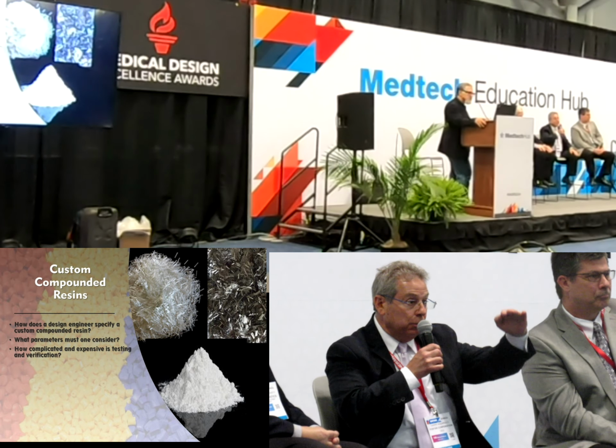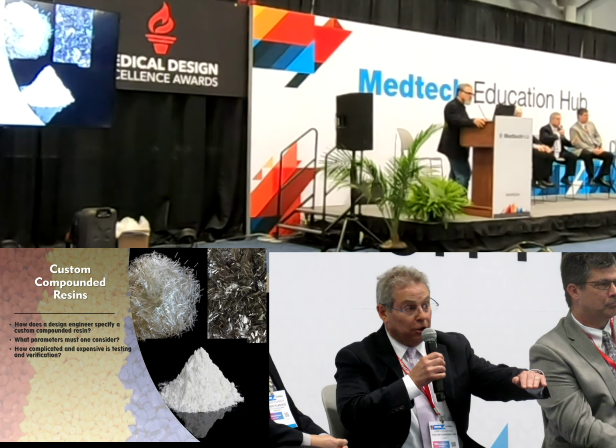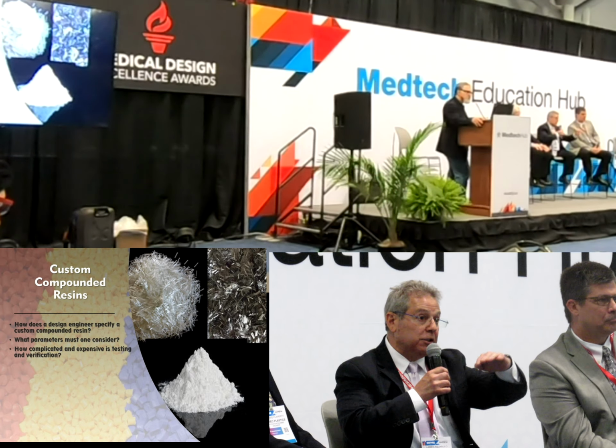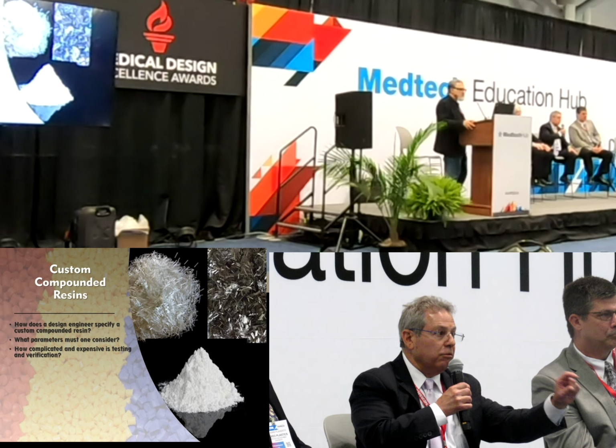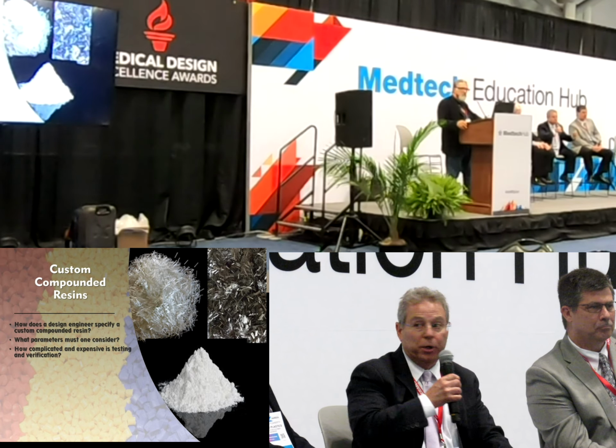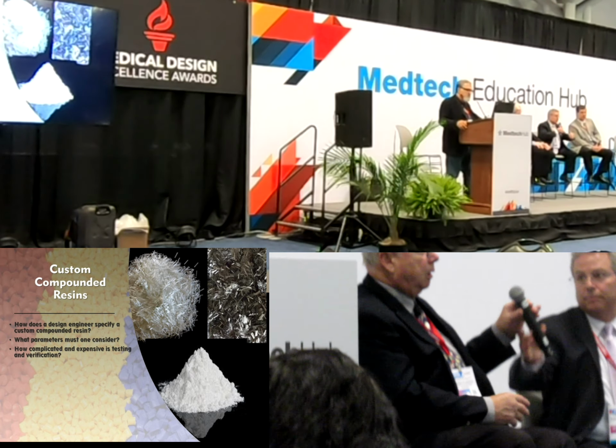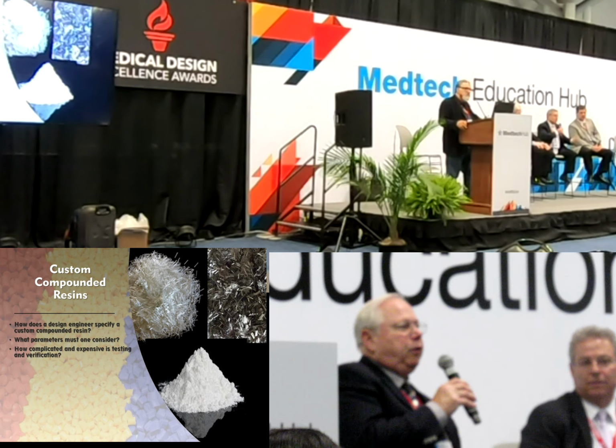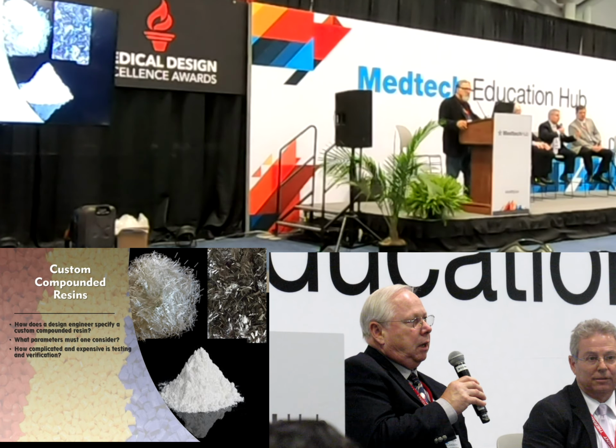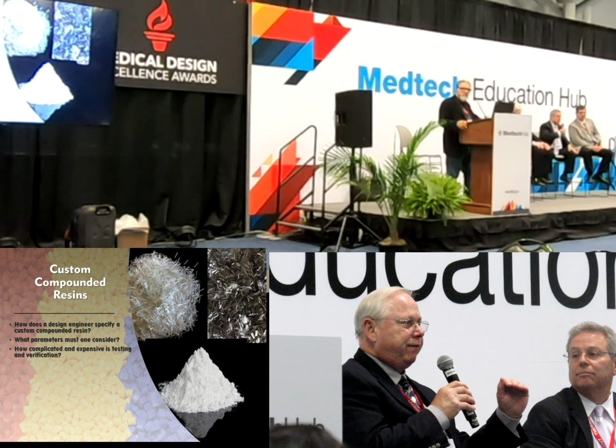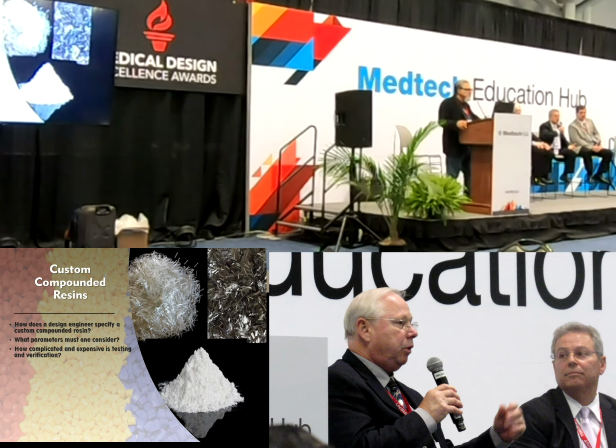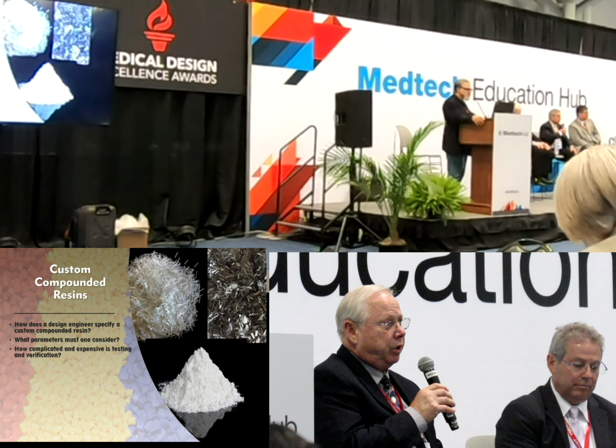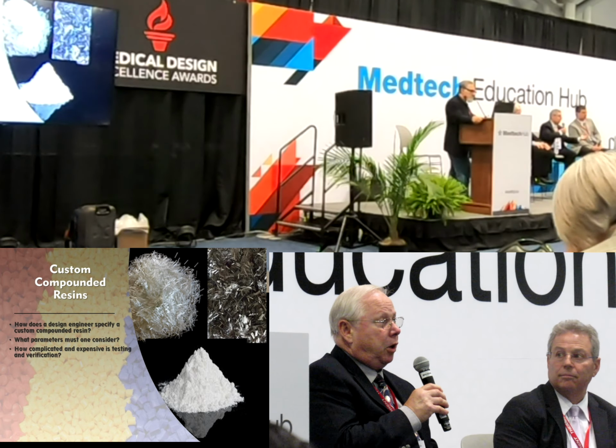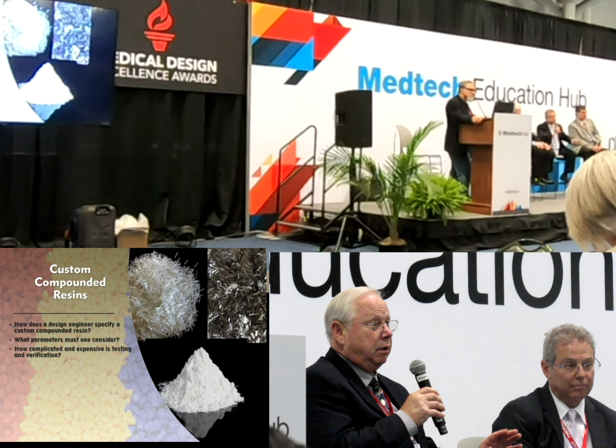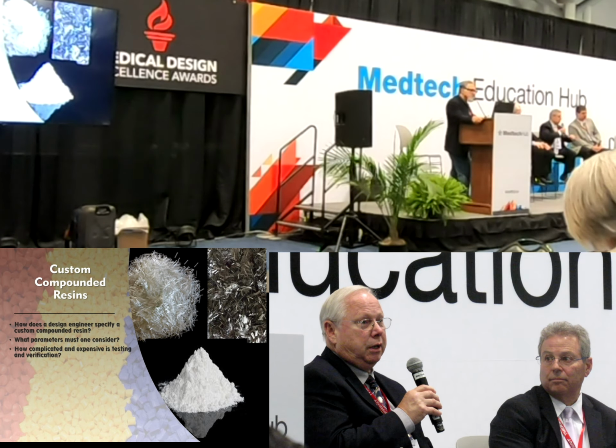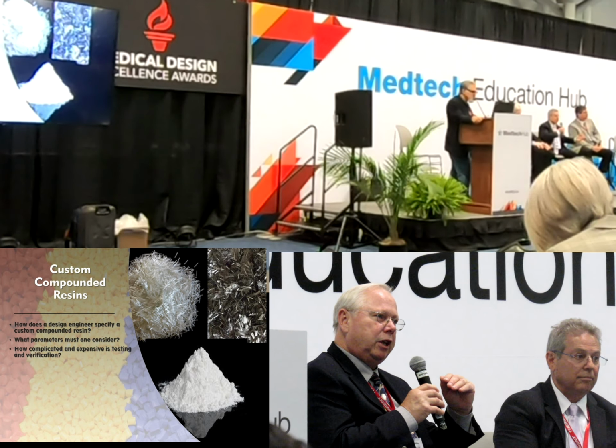Or it could change the particle shape of the polymer. Maybe the pellets are too big if you're going into a micro extruder or a micro molder, so you have to reduce the pellet size either through a melt processing or a grinding process. Those are all things that compounders do. But as Michael alluded to, usually 90% of what we do is we're adding something to the resin to give it some special feature, whether it's color, whether it's lubricity, stabilizers, radiopacity if it's going inside the body.